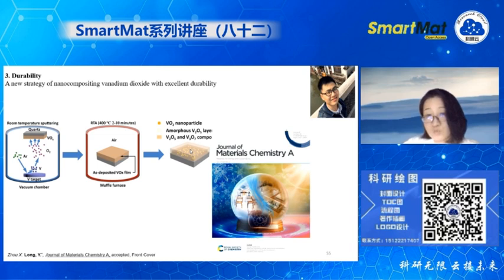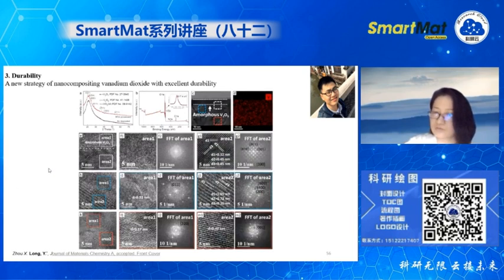So why is this one good? Because V2O5 is the most thermodynamically stable of the vanadium oxides, right? By doing so, we can largely enhance the durability of this vanadium dioxide coating. I think it's 23 years, if I'm not wrong. They have done this X-ray test, so we said it's about 23 years. They have studied a lot. You can see the top surface is amorphous V2O5, then VO2 is inversely distributed among this V2O5 matrix. Once you use PVD, most people fabricate continuous vanadium dioxide films. But using such a very simple way, you can put the VO2 as a composite, like an additive embedded inside the V2O5 matrix. By doing so, you are going to have very high durability.